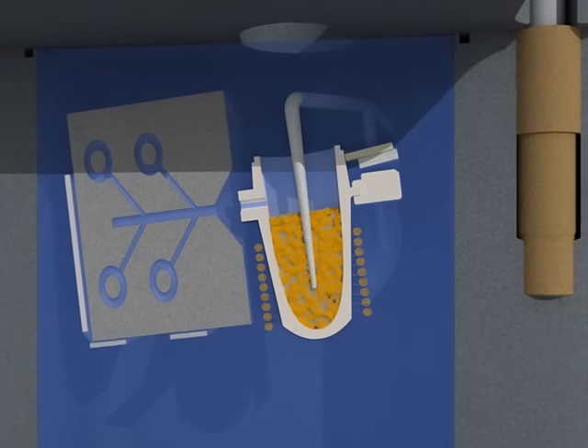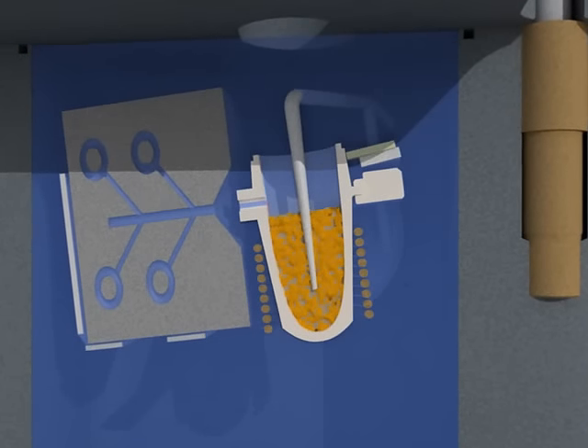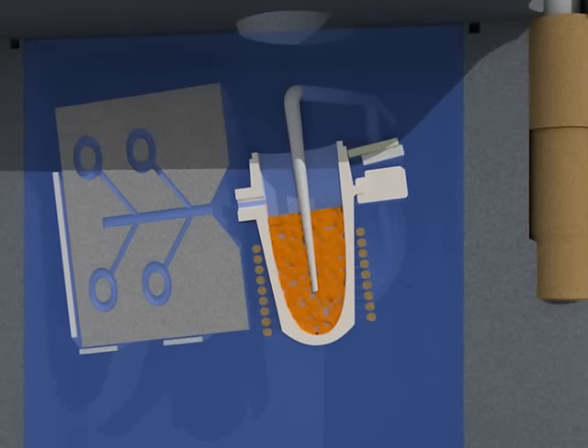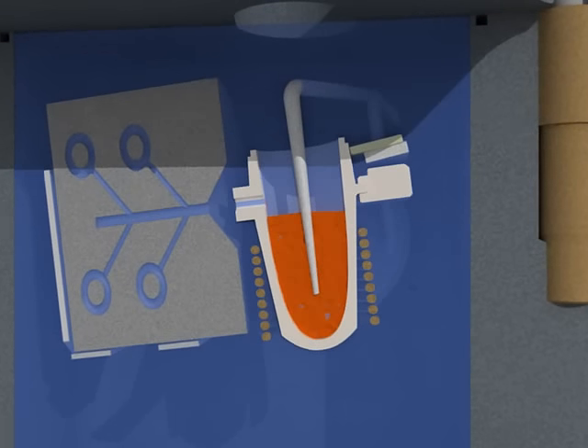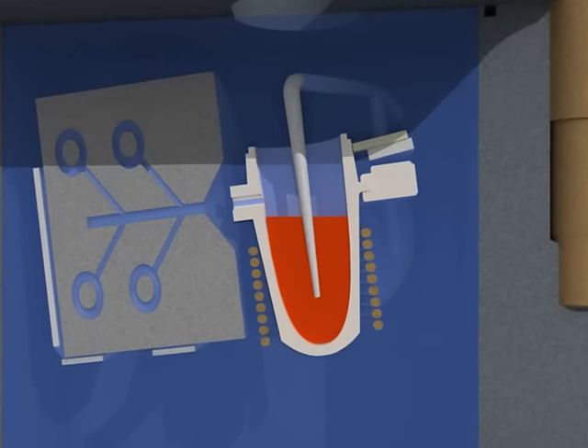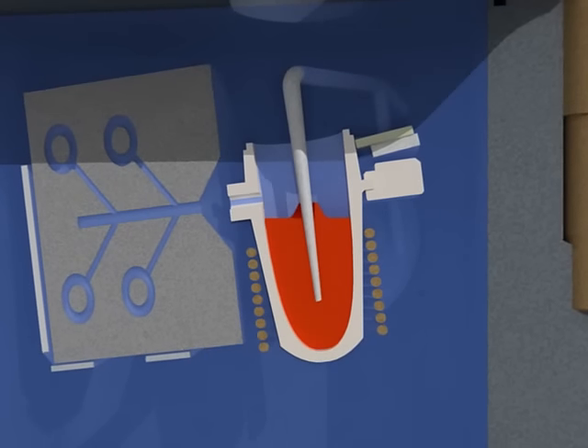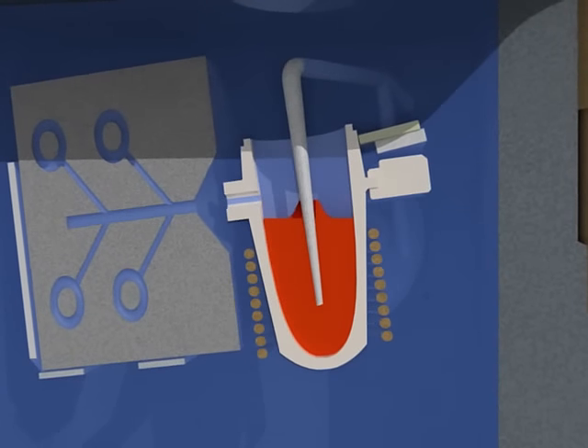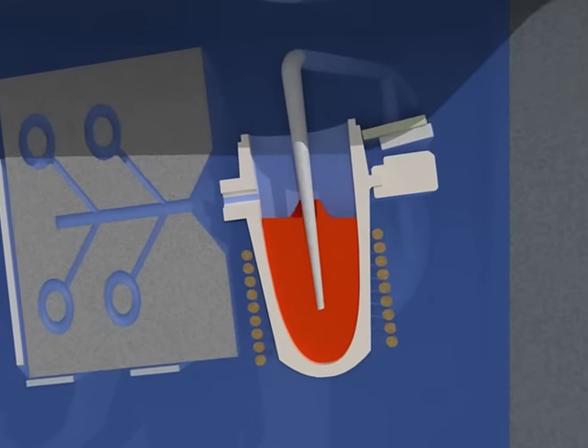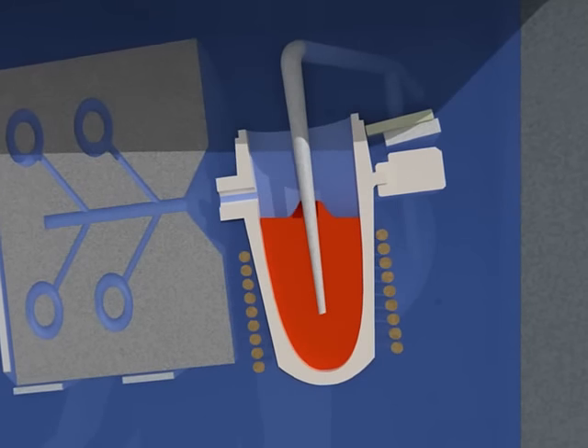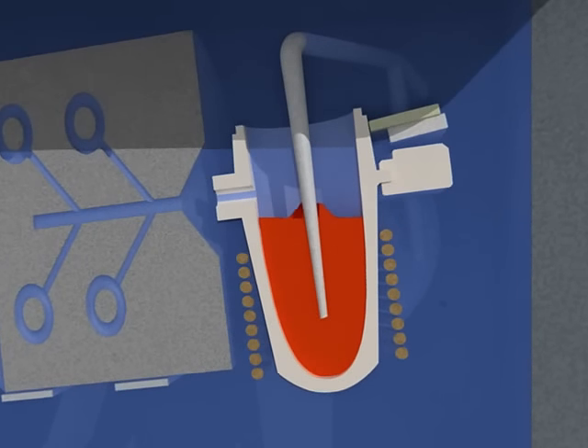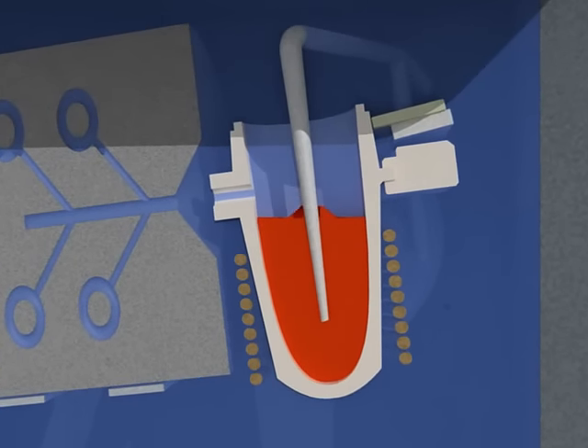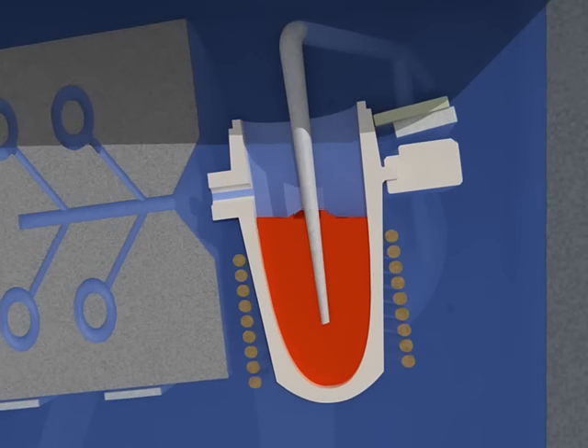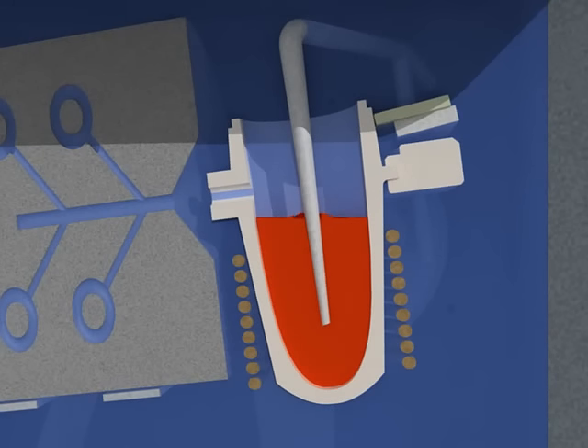The casting temperature is attained, and low-frequency pulses are given to vibrate and mix the molten metal, keeping it homogeneous. Temperature is controlled by an optical pyrometer up to 2100 degrees centigrade for platinum, steel and titanium, and by an immersion-type S thermocouple inside the graphite crucible up to 1500 degrees centigrade for gold, silver and bronze.